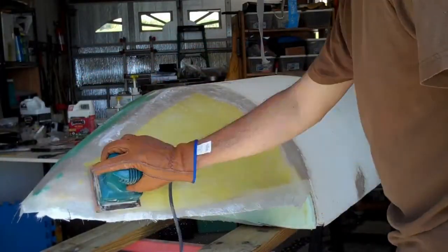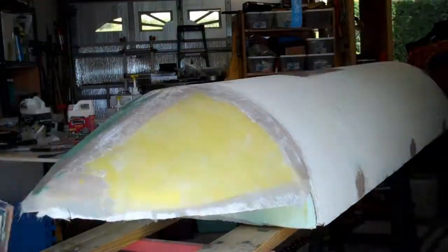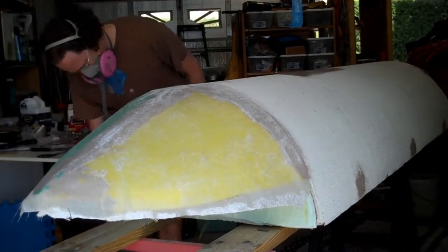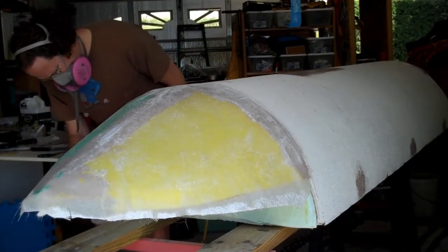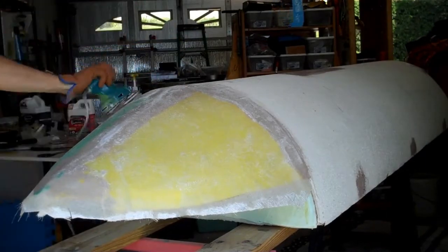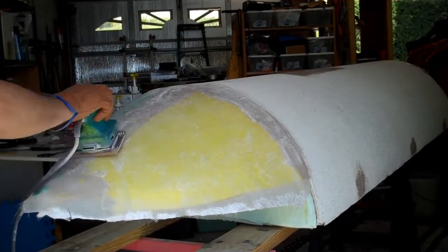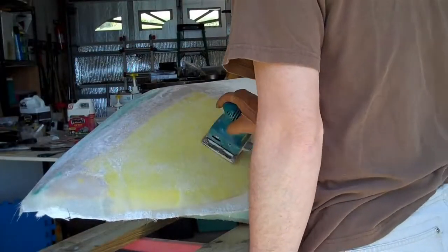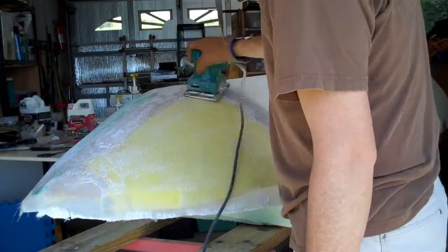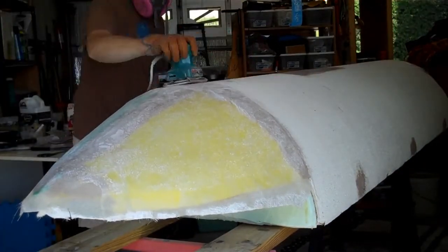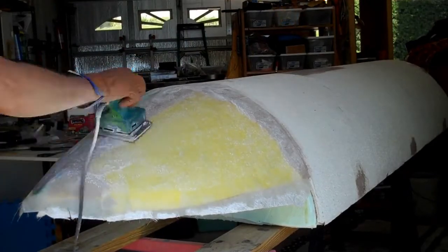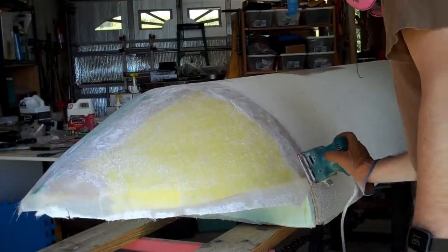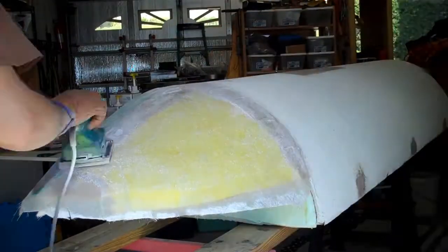After putting chop strand mat on the cylindrical part of the pontoon, I generally just do a single light sanding pass to knock down any fibers that are sticking out and to scuff the surface of the epoxy to get it ready for the next layer of chop strand mat or the final woven fiberglass cloth layer. However, the nose cone has compound curves, so the chop strand mat will sometimes have small wrinkles, which require a more intensive bit of sanding to level things out, seen here.